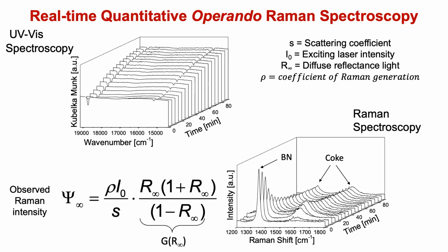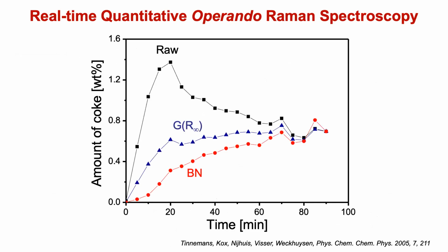I show you here, we mixed it with boron nitride as a reference. And you see that, because of the coke deposit, you see less and less of the boron nitride appearing. So here I show you the quantification: the raw data going up and down makes no sense. And then the compensated version, you see it gradually builds up, and the boron nitride, you see it also. It's not the same, but I would say that is reasonable. Most important, because you make a calibration line, you can put the amount of coke in weight percent. You can get a number on it.